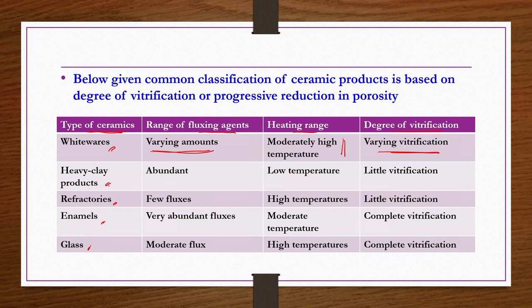Whereas in heavy clay products, fluxing agents are present in abundance, but despite that, vitrification is not high, it is only little. That is because the applied temperature is low. Vitrification takes place better at high temperatures. Okay? So, though here you have abundant fluxing agents, the applied temperature is low, so that is the reason you are getting little vitrification. Then refractories, few fluxes are there, and high temperatures are the range of heating. So, since the fluxes are few, you have little vitrification here as well.